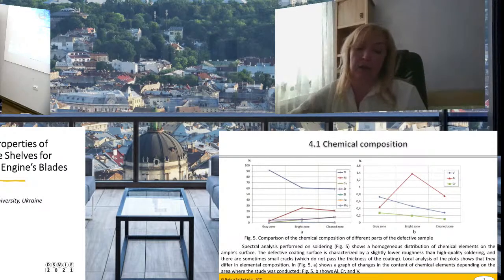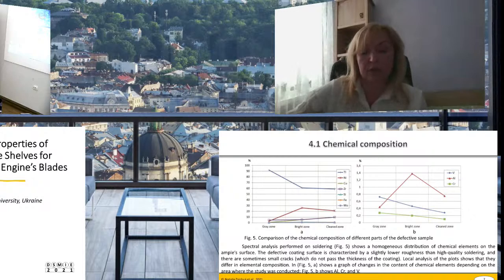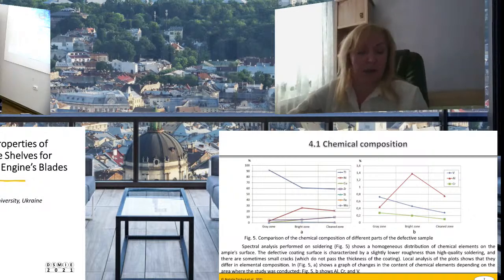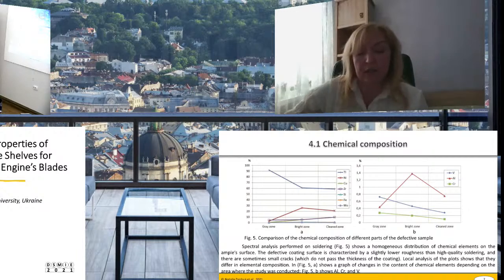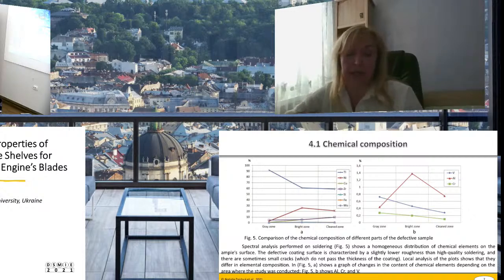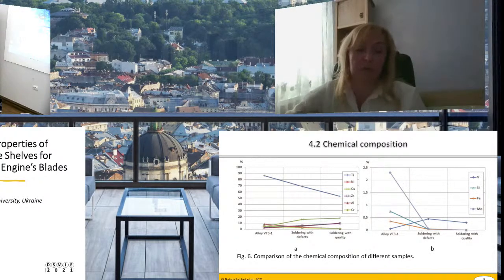Spectral analysis performed on soldering shows a homogeneous distribution of chemical elements on the sample's surface. The defective coating surface is characterized by a significantly lower roughness than high quality soldering, and there are sometimes small cracks which don't pass through the thickness of the coating. Local analysis of the spots shows that they differ in elements. On the next slide, we can see a comparison of the content of chemical elements in different parts of the studied samples, figure 6.